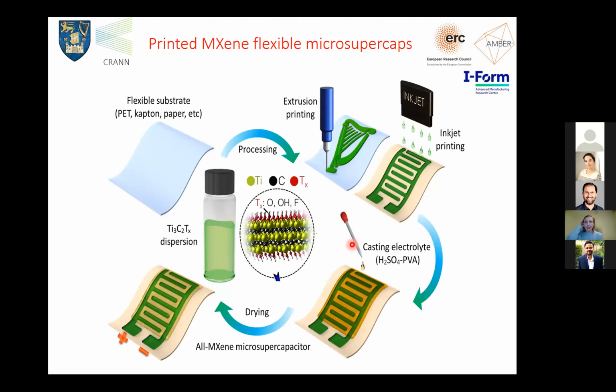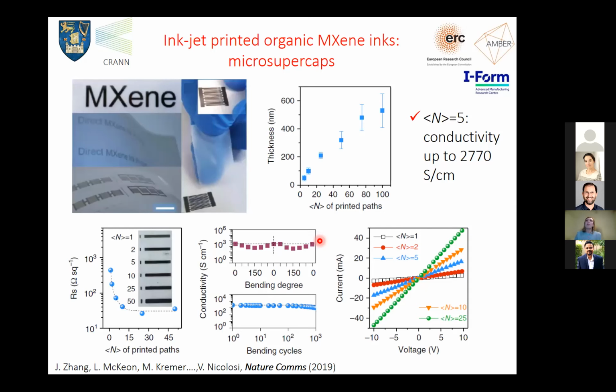The most immediate development was on printing. We do a lot of printing in my group, and I'll show you just a few examples. We developed a methodology to use MXene inks, both by extrusion printing and by inkjet printing. Then we do the normal device build, we cast the electrolytes, and then we characterize them as supercaps. This is an example of some of the devices we printed by inkjet printing from organic solvents, N-methyl pyrrolidone, for example. The beauty of this is that, of course, you can make your interdigitated devices, but you can also have the freedom to build more complicated devices, like in series or in parallel.